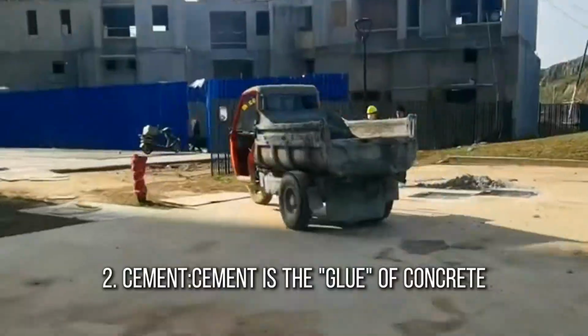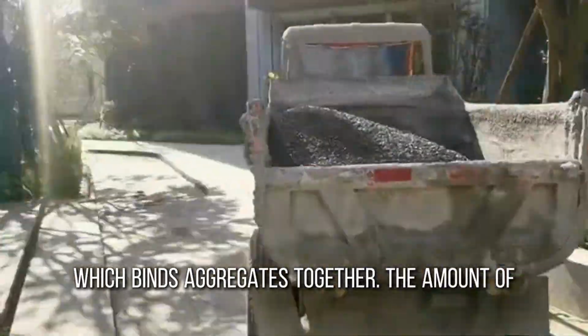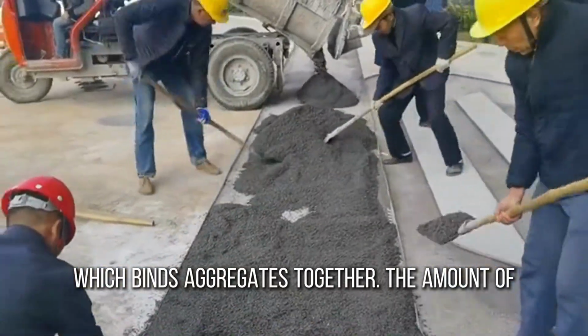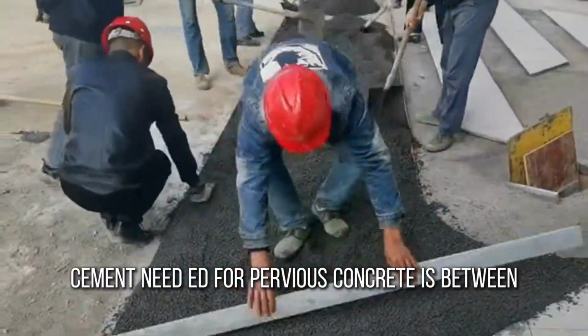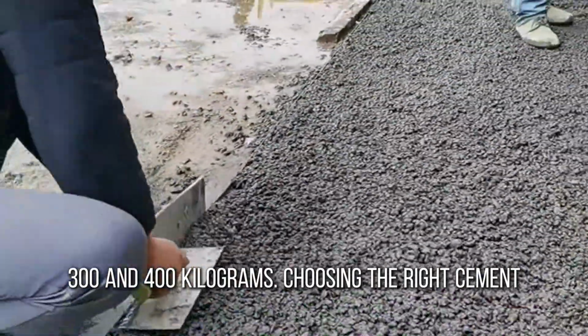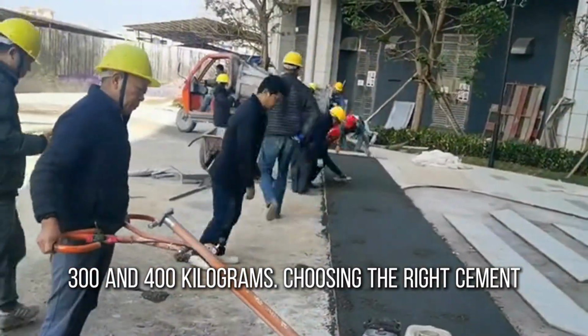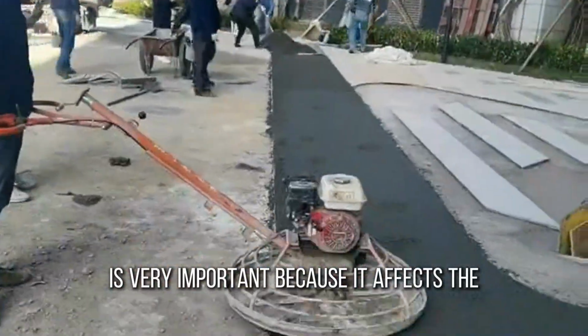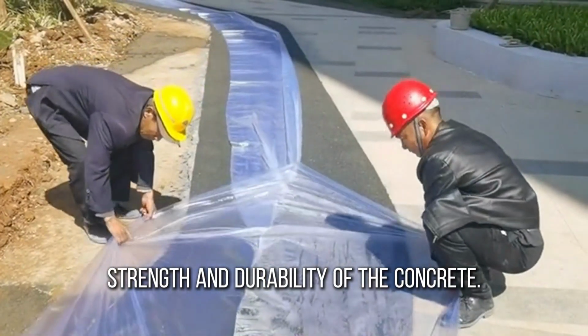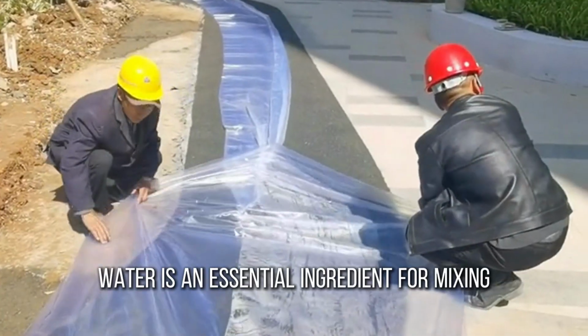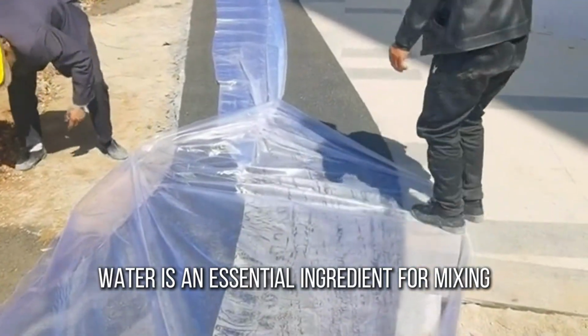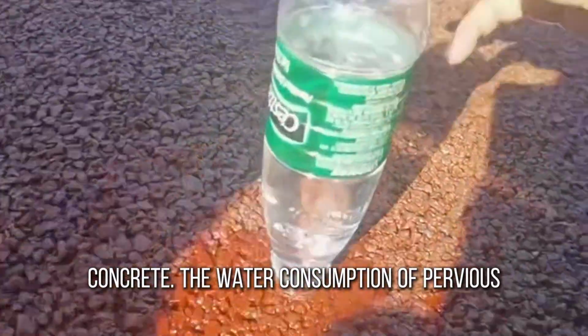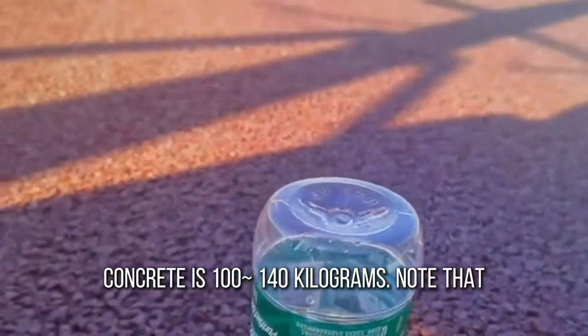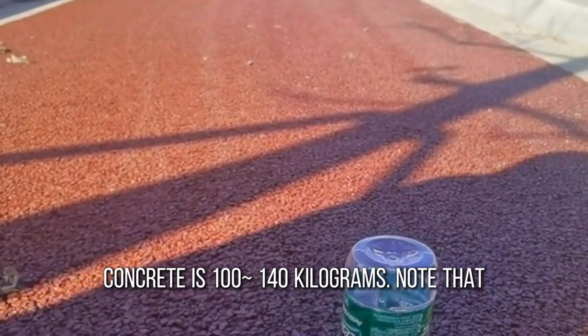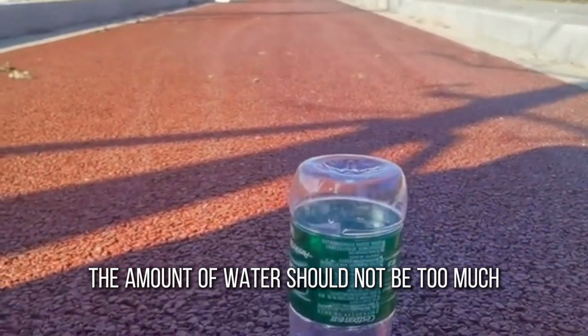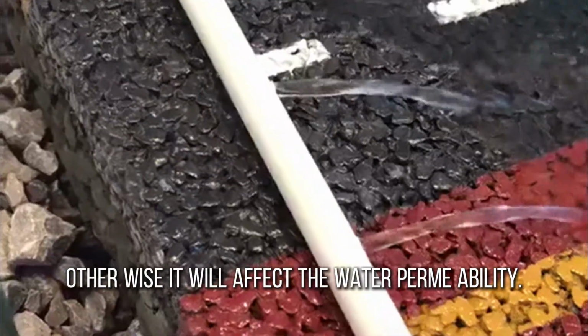2. Cement. Cement is the glue of concrete, which binds aggregates together. The amount of cement needed for pervious concrete is between 300 and 400 kilograms. Choosing the right cement is very important because it affects the strength and durability of the concrete. 3. Water. Water is an essential ingredient for mixing concrete. The water consumption of pervious concrete is 100 to 140 kilograms. Note that the amount of water should not be too much, otherwise it will affect the water permeability.